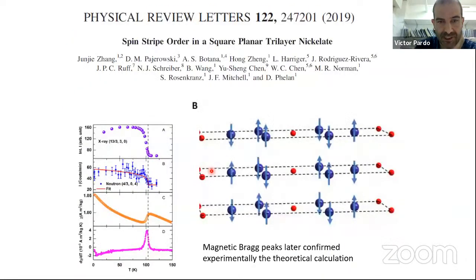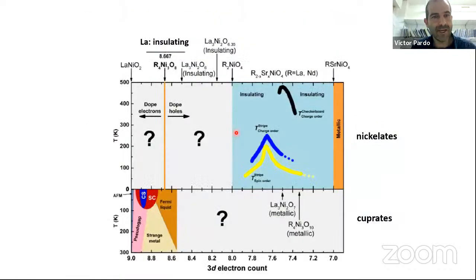So our colleagues 3 years later, what they did was, okay, let's try to find the spin structure with neutron experiments, and they actually confirmed our prediction. They saw that these stripes had the actual charge and magnetic ordering that we had seen from our calculations, which shows DFT calculations are pretty good in predicting that kind of structural and magnetic distortions.